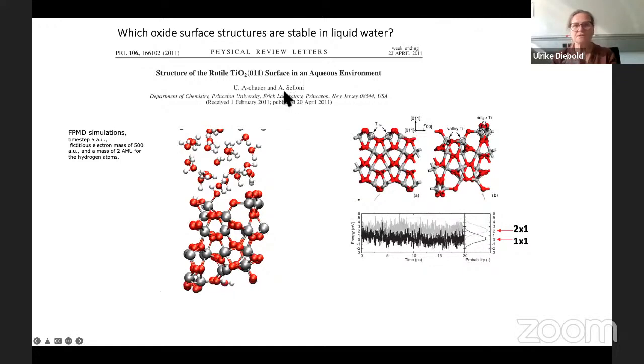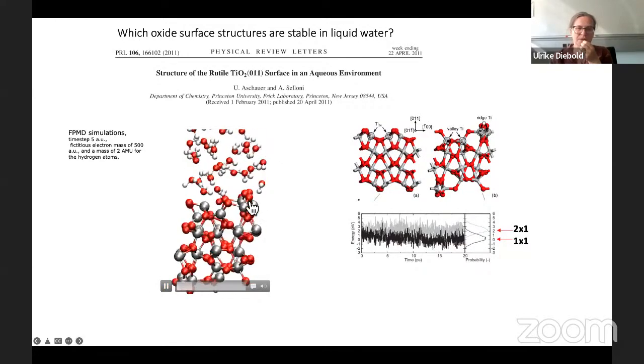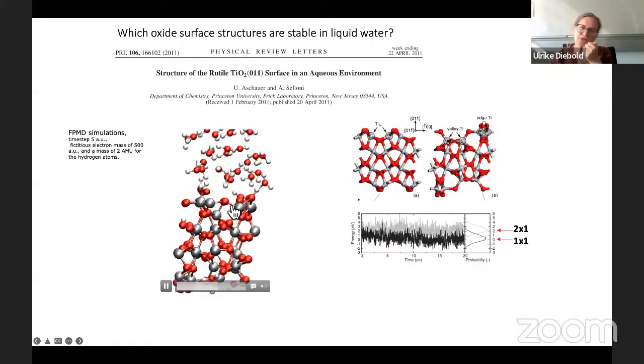We know that, and actually this is work from Annabella Selloni, and we've published papers together showing that in ultra-high vacuum it reconstructs. She starts with this surface with the identified reconstruction, so the top surface atoms look a little bit different. Then together with Ali Hassanali, these are first principles molecular dynamics simulations for a relatively long time. This is liquid water, and the liquid water changes the surface. Its surface structure after a while really will change. It will go back and change towards what we call a 1-by-1, a bulk-terminated surface. You can see there is some bond that formed here.